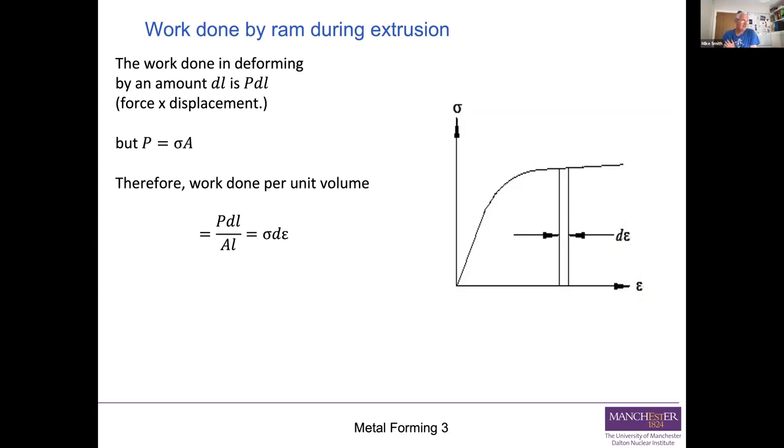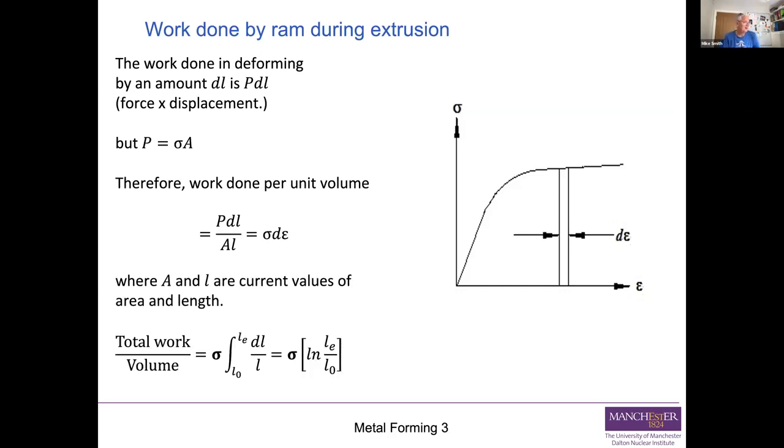So we've now got a relationship between the dimensions of the billet, the load, and actually the stress strain curve. So A and L are the current values of area and length. So what we can now do is integrate that up to generate the total work per unit volume. And what we're doing there is we're actually integrating the stress strain curve. So we're integrating this current level of stress